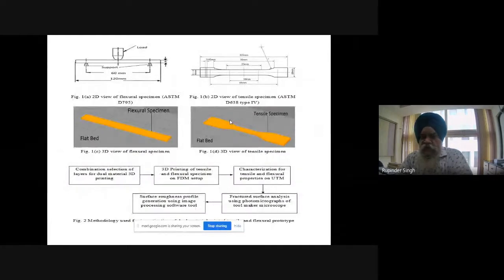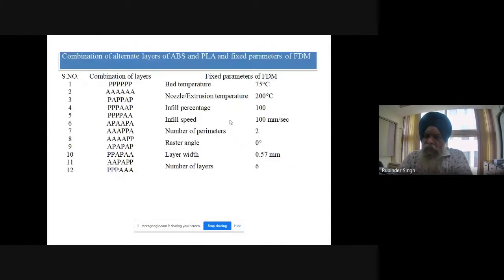So again, like the previous case, some of the samples have been printed in the form of tensile coupons as well as flexural coupons. Here we selected two materials. One was PLA and another was ABS, right? So I fixed some of the parameters of the fused deposition modeling printer, like the bed temperature, the nozzle temperature, infill percentage, infill speed, number of perimeters, raster angle, layer width, number of layers. These types of parameters have been kept fixed, right?